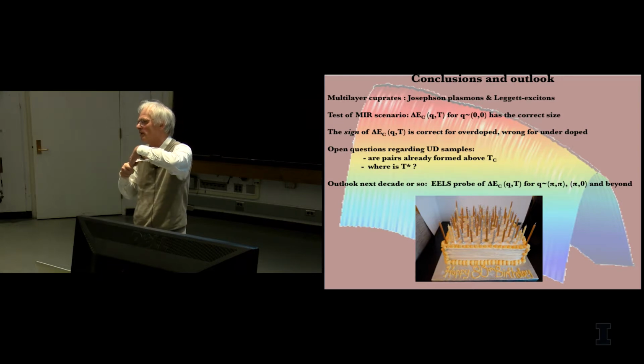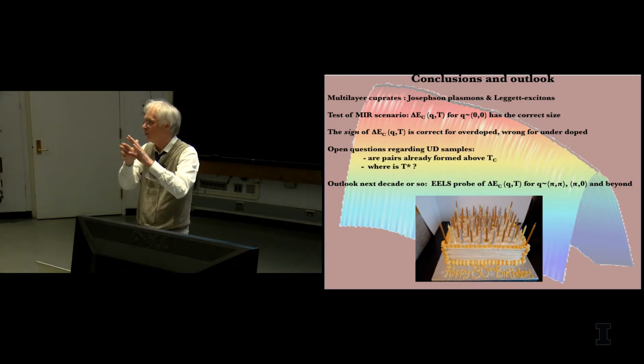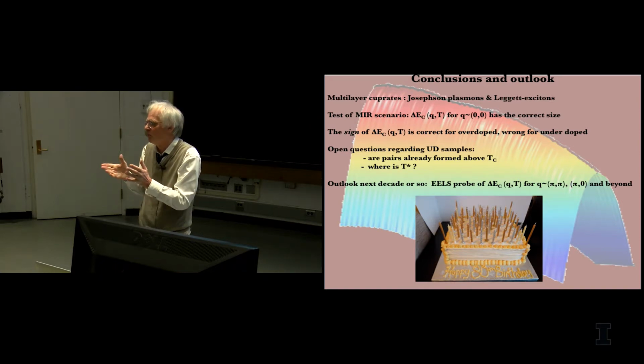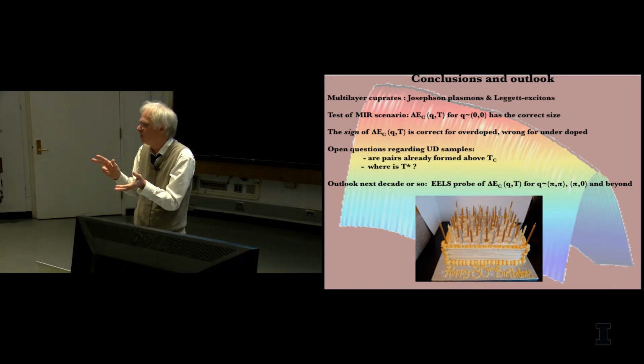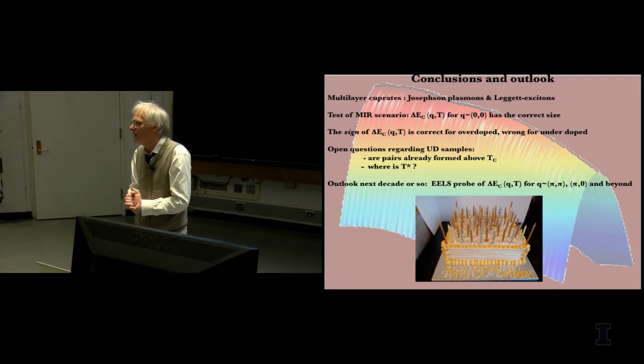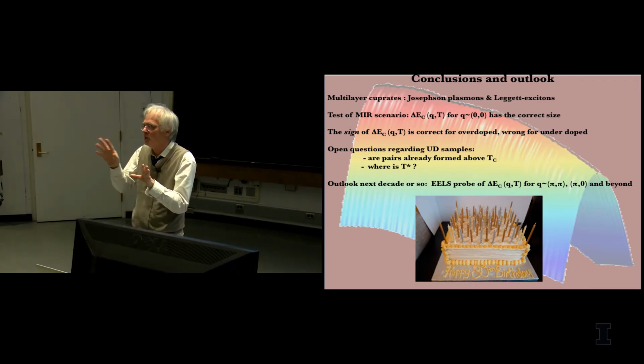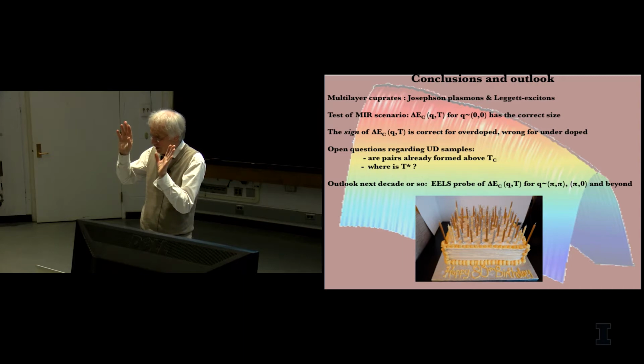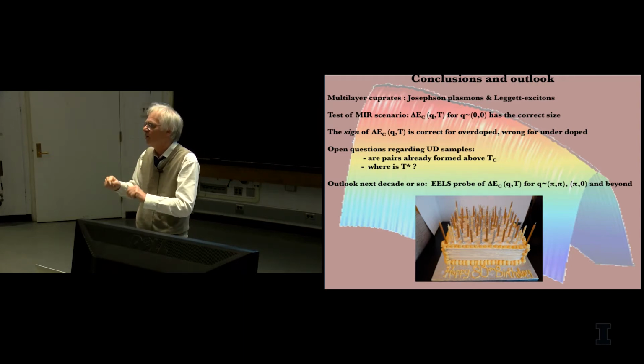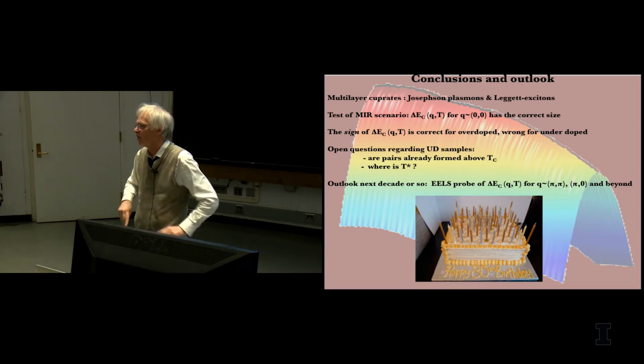You get it from a different sum rule, which concentrates on the optical conductivity at low frequencies. But you can always pose the question: are we looking at really independent quantities, or quantities that are still related through Kramers-Kronig relations? I guess we are. Although in principle, you could imagine that the two measurements that we do, ellipsometry with this sum rule, optical conductivity with a different sum rule, really give different types of information about the material. But yeah, they do cross 0 at the same point as a function of doping.